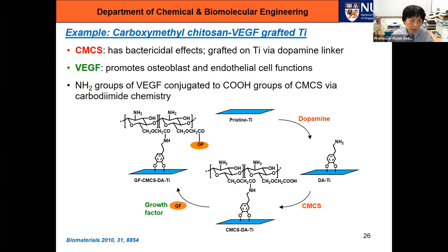This is an example using carboxymethyl chitosan as the base layer because it has bactericidal property. And then we are going to use VEGF, which is vascular endothelial growth factor, for the osteoblasts. The reason why we pick VEGF is because not only does it promote osteoblast functions, it also promotes endothelial cell functions, which is important for implants. The method of changing the surface is easy. We first use dopamine to act as a surface linker because it has a catechol group, so it sticks well to titanium. Then we graft on CMCS using carbodiimide chemistry, followed by the grafting of VEGF, again by carbodiimide chemistry. The results are shown here.